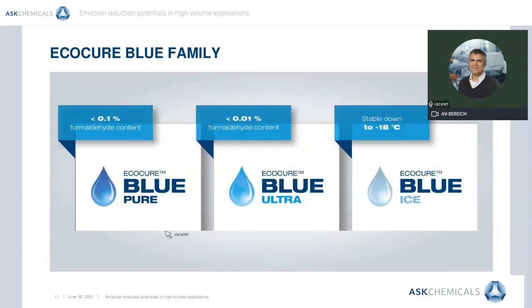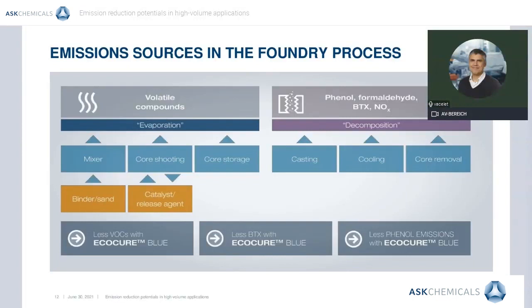In addition to the initial formula, renamed here EcoCure Blue Pure, the EcoCure Blue range is extended with a solution with less than 0.01% free formaldehyde, called EcoCure Blue Ultra, anticipating future changes in legislation, or reformulated in part to increase resistance to storage at low temperatures. That is the EcoCure Blue Ice. This family is in constant development with customized solutions possible, and the forthcoming arrival of a second generation of product with even better technical performance.